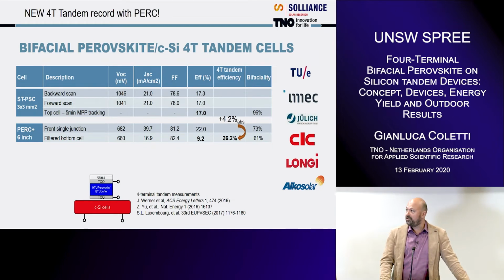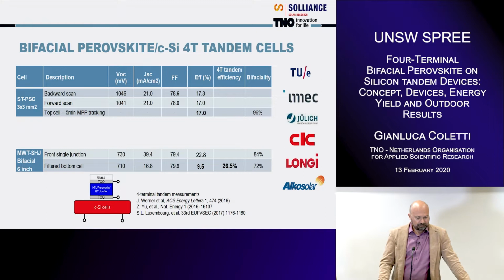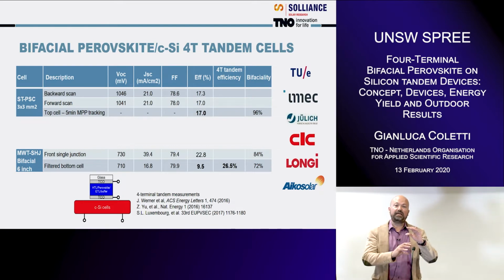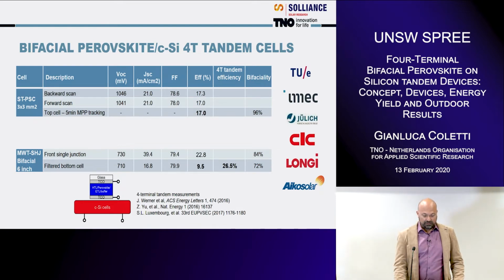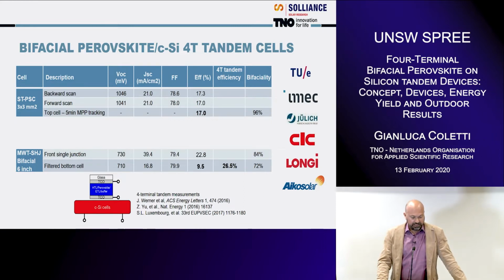Of over 4% on a technology, the silicon technology that is already in mass production. Then we put our more advanced device, a heterojunction with back contact. Contact in the rear side is an MWT, which has an efficiency of 22.8%. When you put these under the perovskite, it generates 9.5%. Therefore, in total, you have an efficiency of 26.5%, and a bifaciality that is very interesting, 84% on the single junction use, and 72% when it is filtered with the bottom device.